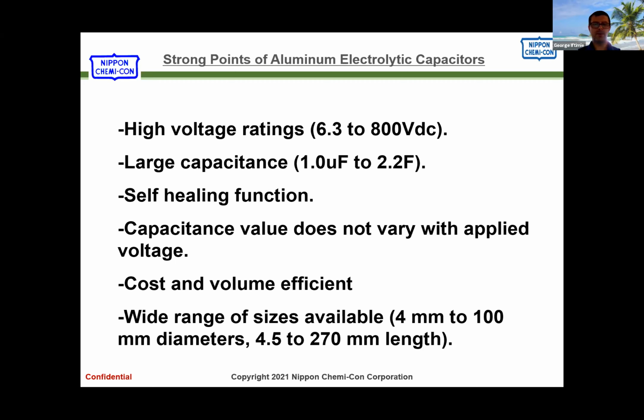In order to build aluminum oxide, of course, aluminum oxide is just aluminum and oxygen. The foil is made of aluminum, so that's easily present. The oxygen is a little bit more difficult to obtain, especially in a polymer capacitor. So polymers, as I mentioned earlier a little bit in a presentation, have a healing function, but it is very, very slow. With aluminums and hybrids to a big extent, if you have an overstress condition and the capacitor didn't fail catastrophically, then essentially you can assume that it healed correctly and you don't have to worry about cumulative types of stresses. With a polymer capacitor, you do have to worry about that.